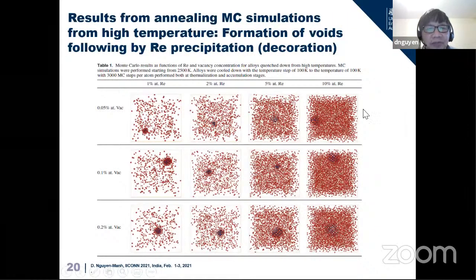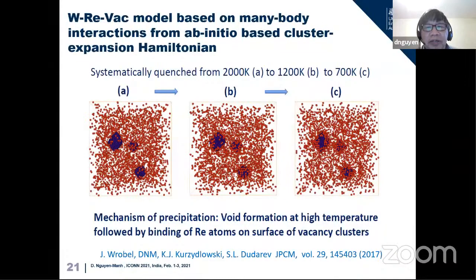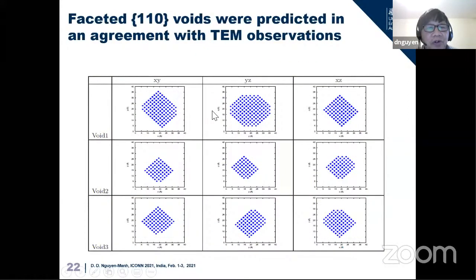We see the void at different rhenium concentrations and different vacancy concentrations happening when we're quenching down from 2,500K to very low temperature. And this feature can be shown at the irradiation temperature, corresponding to the experimental data that I showed earlier, where you can see that we have 3 voids happening here. If you look at the void separately, we can see that it's faceted in the 110 direction, which is exactly what the high resolution TEM image showed earlier. But here we show a quantitative picture of the void formation from ab initio calculation.